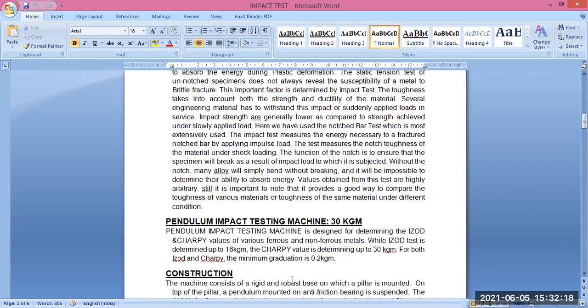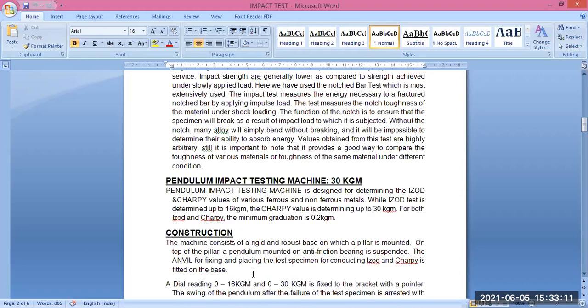Now what we have is this pendulum testing machine. We have seen a pendulum which is swinging from either 85 degrees for Izod or 140 degrees for Charpy, which is always away from the test specimen itself. This pendulum machine is designed for determining the Izod and Charpy values, and the Charpy value is determined up to 30 kg meter. So for Izod it is around 16 kg meter, and for Charpy it is around 30 kg meter. For both Izod and Charpy, the minimum graduation is 0.2.